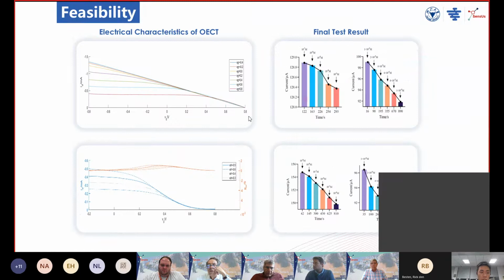For the whole device, the transfer characteristics curve shows an optimum modulation effect at a fixed gate voltage of 0.4 volt. And the final test shows our device is most sensitive at a virus concentration around 10 to the power of -5, and the limit can also be lower than 10 to the power of -9. With electrical amplification, we can achieve even the scale of 10 to the power of -11. So that is pico level, I think.